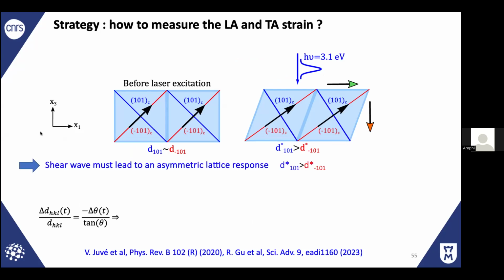We did that for bismuth iron oxide, so nothing new, except the fact that we developed a methodology to measure the shear. If you look at the cubic symmetry here, if you have a shear stress, you see the red interplanar distance will be different from the blue. In a cubic symmetry, 101 is equivalent to minus 101. But if you have shear, you can break that symmetry. This is exactly what we analyzed to get back the shear.